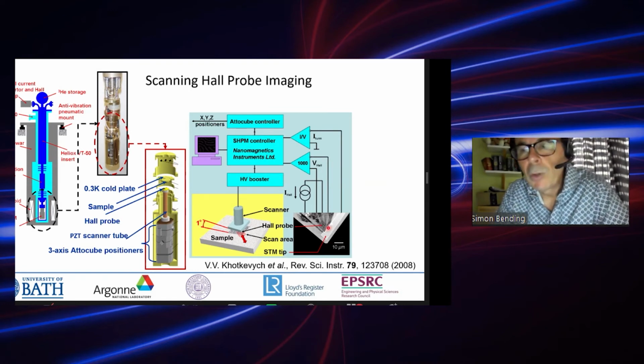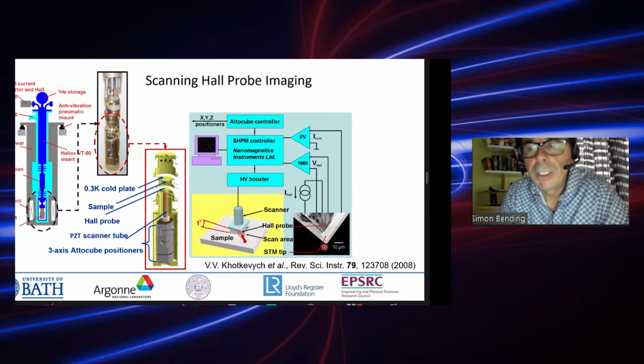Our Hall sensor, really all of our technology is tied up in the Hall sensor, but it has a submicron cross, which is patterned as near as we can to this integrated scanning tunneling microscopy tip. It really is a poor man's STM tip. We create a deep etched mesa here, and then we deposit a thin film of gold over the edge of the mesa, and then the corner here provides us with a poor but satisfactory STM tip, and we can use that to approach and find the surface and map the surface if you wish.